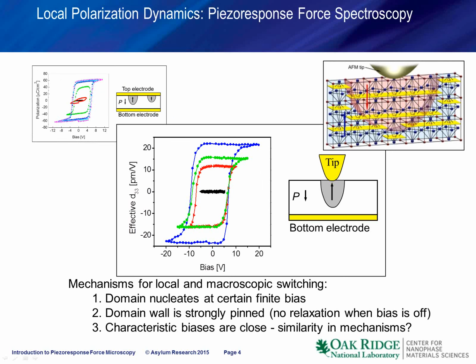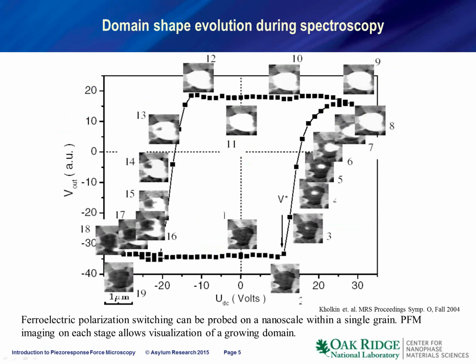So for a small bias window, nothing much happens. For a larger bias window, the loop opens up and then it opens up and saturates. And even the width of the loop for the macroscopic case and the local case are almost the same. It's 8 versus 12 volts. However, in this case, the mechanism for the loop formation is completely different because we have only one domain forming below the tip, and in some sense we study a deterministic process of local bias-induced transition. So the theory behind this hysteresis loop is totally different, and this is very interesting to study.